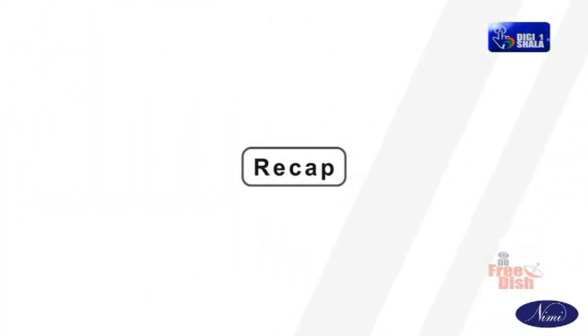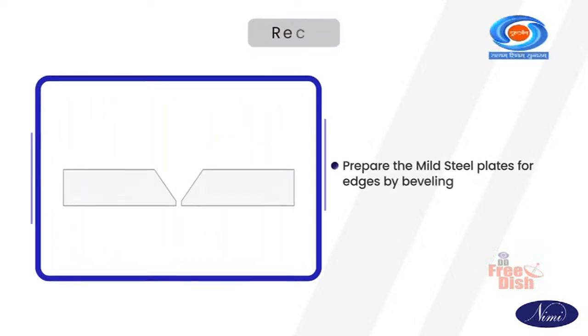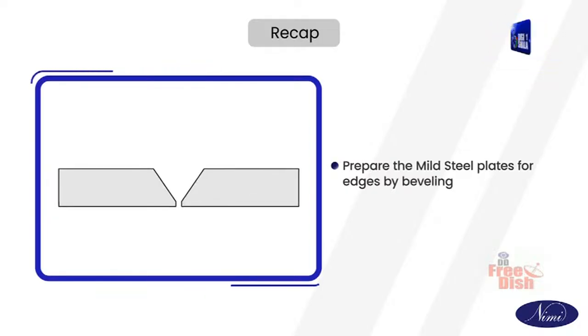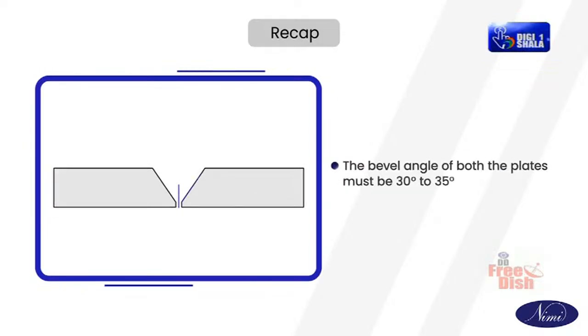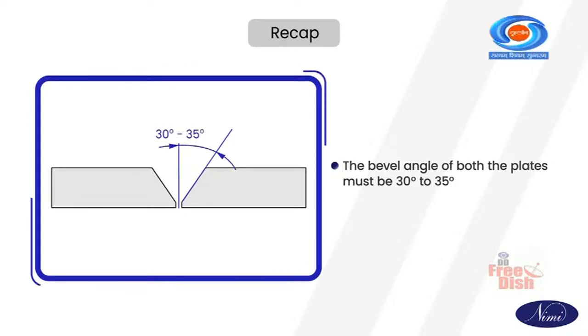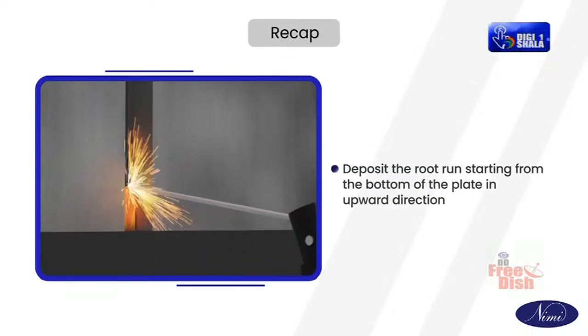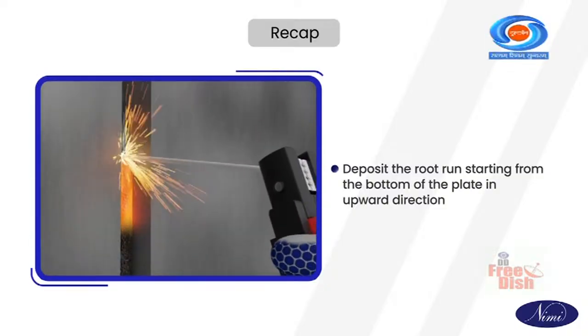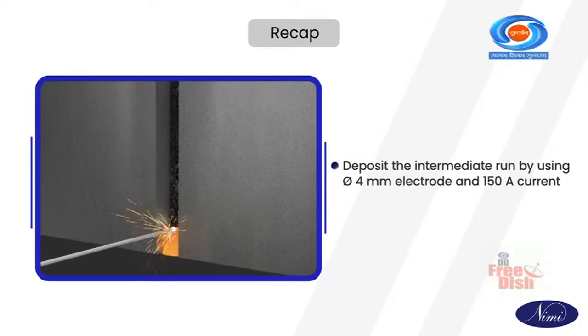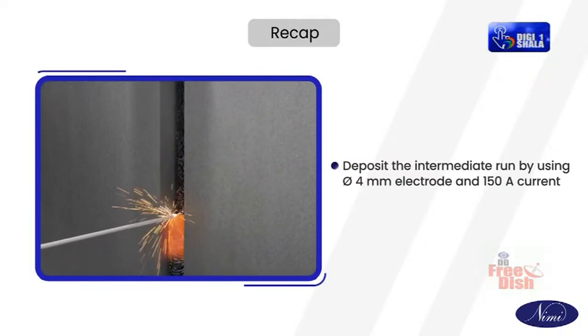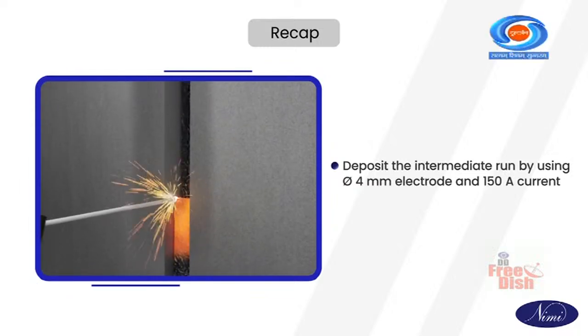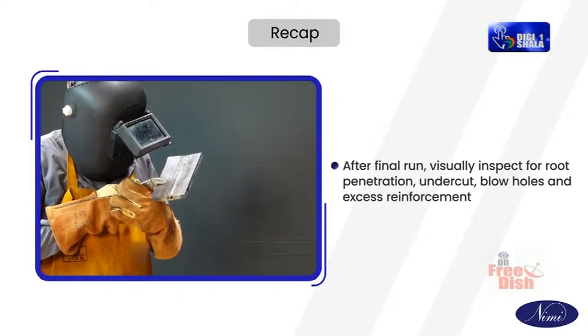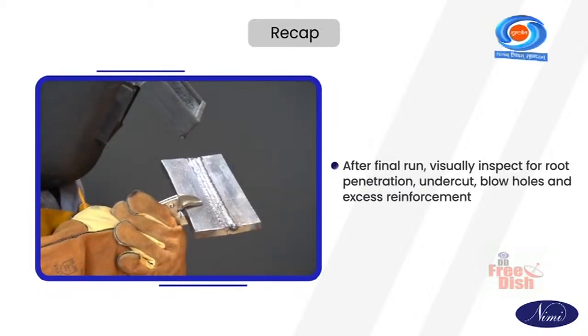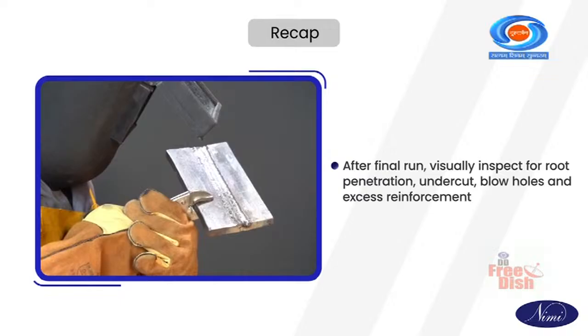Let's recap the key points discussed. Prepare the mild steel plates for edges by beveling. The bevel angle of both the plates must be 30 degree to 35 degree. Deposit the root run starting from the bottom of the plate in upward direction. Deposit the intermediate run by using 4 mm diameter electrode and 150 ampere current. After final run, visually inspect for root penetration, undercut, blowholes and excess reinforcement.